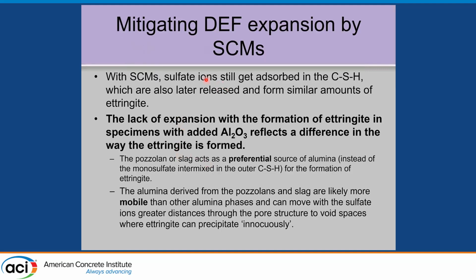So what's going on? Why are they mitigating? With SCMs, sulfate ions still get absorbed into the CSH. And they're also later released to form similar amounts of ettringite. When we measured the amount of ettringite in the mix with SCMs, it was pretty similar to what you'd get with the ones that expanded. But it comes down to where the ettringite forms, whether there's expansion or not.